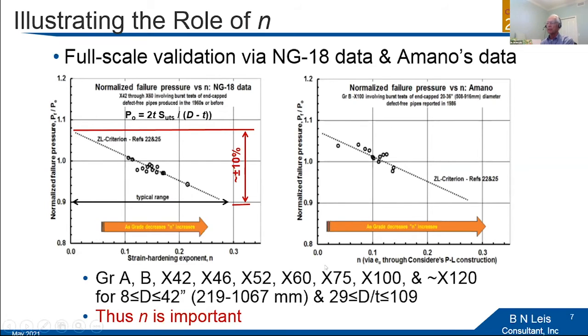Similar results here. Bottom line, and it's really the critical piece of this from the point of view of predicting failure reliably in pipeline systems: we have a wide range of grades that fit this model, from the earliest grades to the most recent modern grade. This happens to be a Japanese steel that's close to X120. Covers a wide range of diameters and covers a wide range of wall thicknesses.